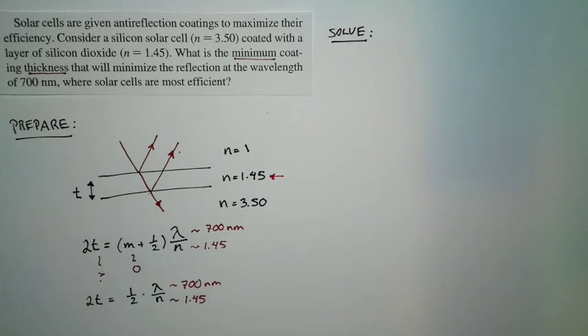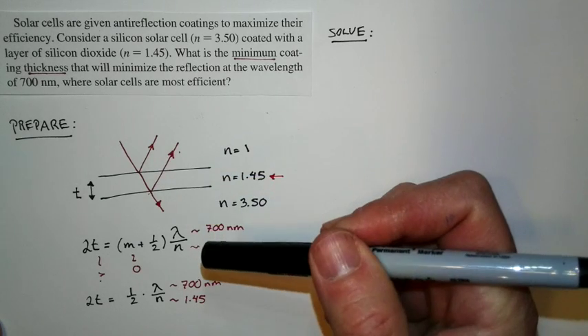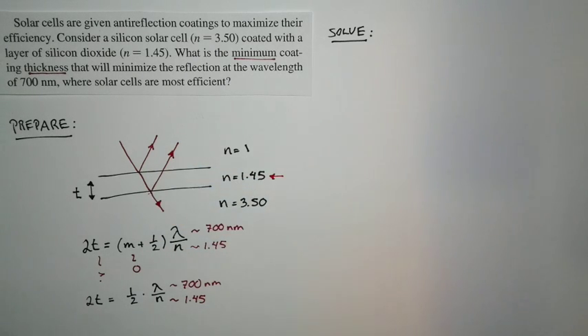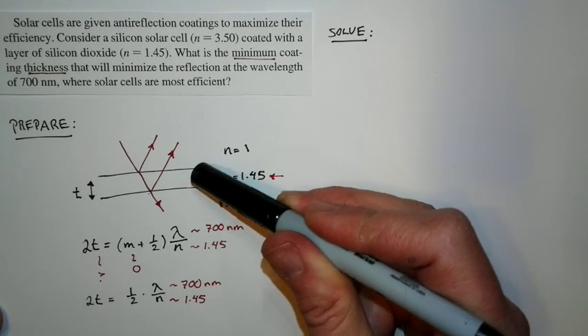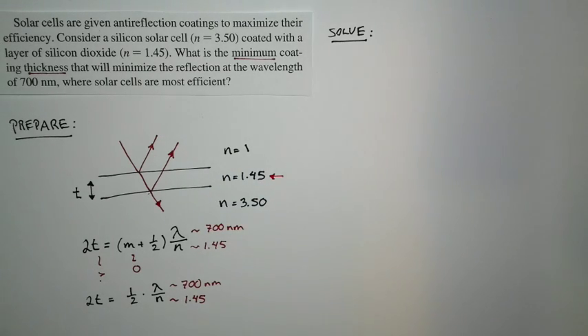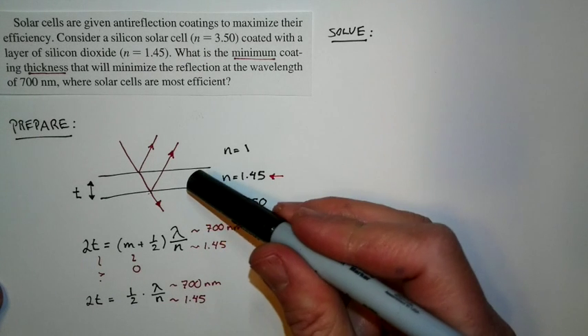With this setup, we're ready to solve. But before we solve, let's think about what our answer is going to look like. I want to have a destructive interference between these two. And I get a destructive interference when the path length difference is half a wavelength. And it makes two transits through the layer. And so I expect this layer thickness to be significantly smaller than the wavelength of light. And that's okay. The wavelength of light on an atomic scale is actually pretty big. And so it's going to seem like a thin film from the point of view of the light. But from the point of view of the atoms, it's pretty thick. An atom is like a tenth of a nanometer in size. And so we can stack a lot of atom layers here.